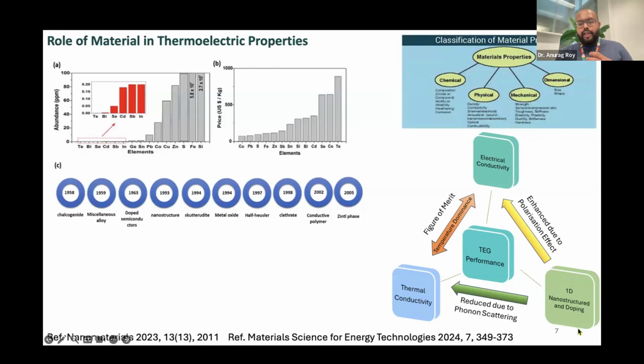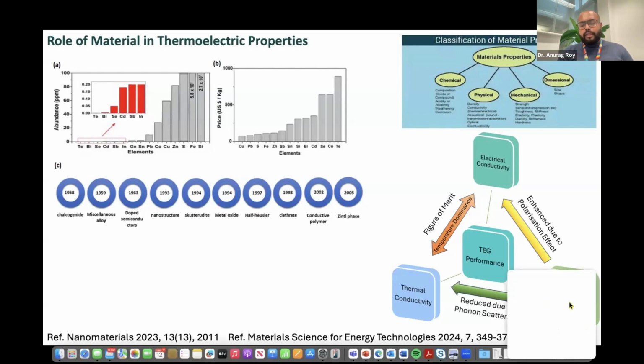On the other hand, if we look at the nanostructure and doping effect in relation to electrical conductivity, there is an enhancement due to the polarization effect. For example, if we take a 1D material compared to 0D, or if we take 3D or some specifically oriented crystal structure, there is definitely a high chance of polarization effect and high chance of electricity production. And on the other hand, for the thermal conductivity and the nanostructure, the relation between them is to reduce phonon scattering. The lower the phonon scattering, the more we can reduce the thermal conductivity, and that's a benefit for getting high thermoelectric efficiency.